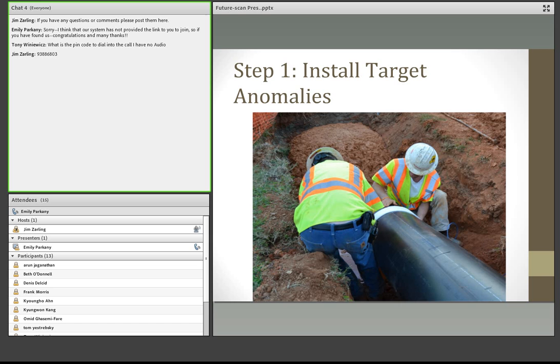In the actual project, the first step that we did was, as they were installing the pipe, in the last 40 feet of the pipe, we installed our target anomalies. These target anomalies were basically a packaging foam. So think of what you would wrap something breakable in before you send it out in the mail. That's really what we used. The reason that we could use this foam as a void is because it has a different dielectric constant than the surrounding soil. And so any sort of radar would be able to pick up that change in dielectric constant.